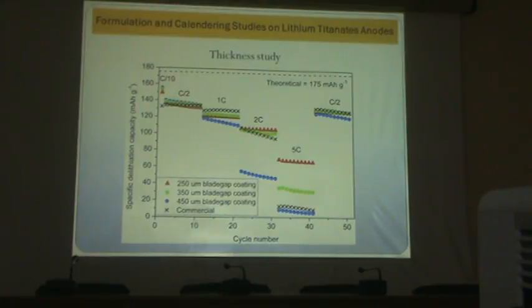Now we did a thickness study, to see how varying the thickness of the anodes affects performance. These C rates are nothing but how fast you can charge and discharge your batteries. Luckily we got a commercial sample. There is a company called Altair, and they gave us a commercial lithium titanate anode to check how good their process is. They coated the electrode and gave it to us. We just made button cells out of it and tested. You can more or less see that up to 2C, all of the button cells are performing quite well. But at a very high rate, 5C, you see that only 250 sustains, and the others fail.